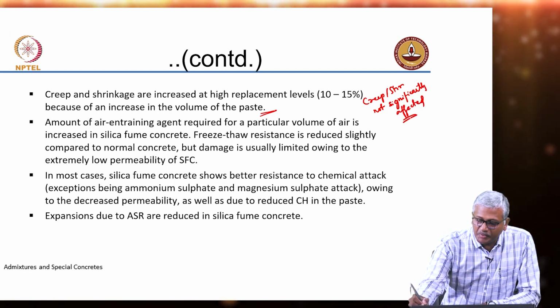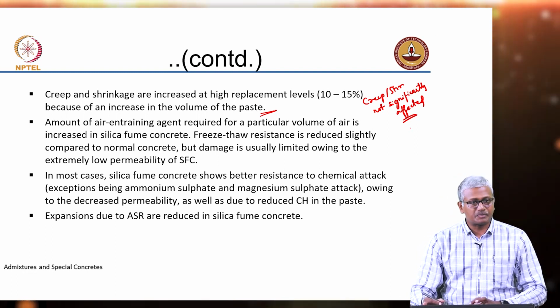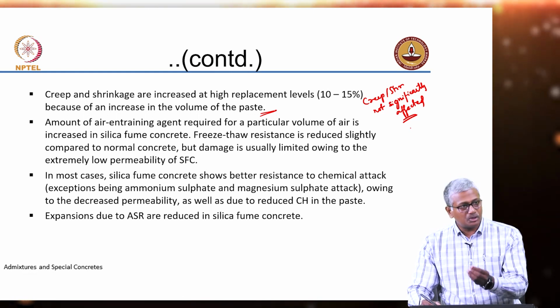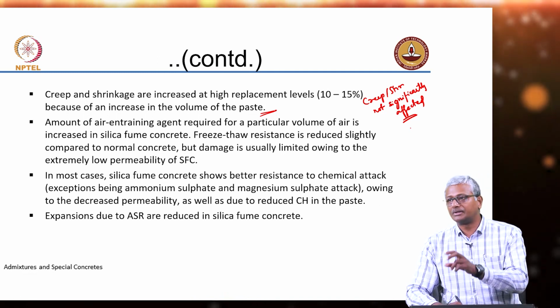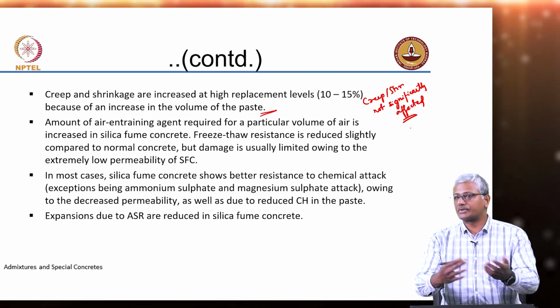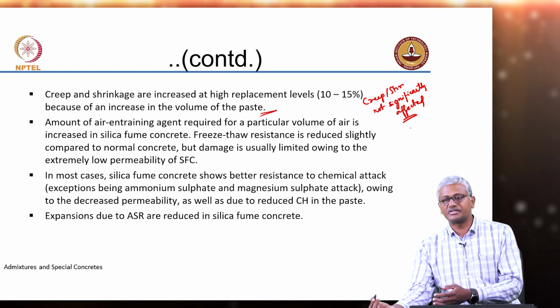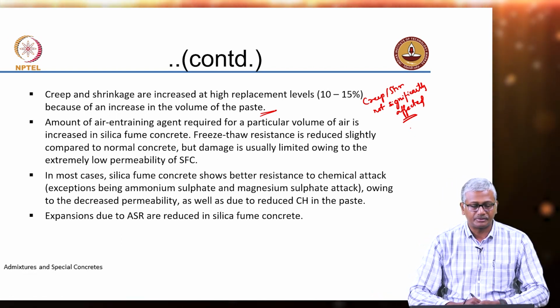That is why in research papers you never find a very clear cut understanding of what happens when cement is replaced by mineral additives to the creep and shrinkage property. So, that also means that when you are designing concrete which has these mineral additives, you need to evaluate these properties and get an estimate, so that you are not using the wrong kind of coefficients that are prescribed in the IS 456, right. IS 456 or any other design guide gives you coefficients that you use for creep. Now, these creep coefficients could be quite different if your cementitious materials combination starts changing.